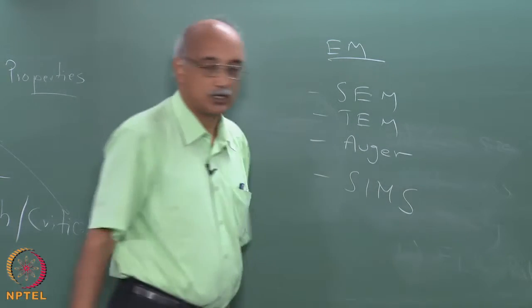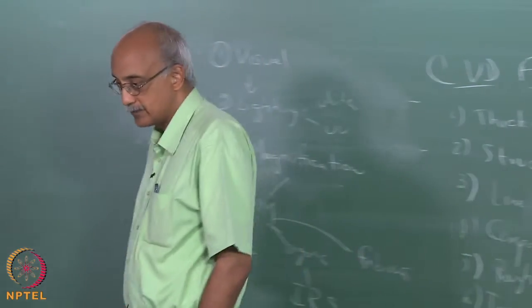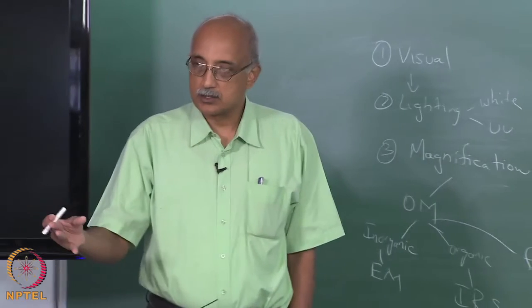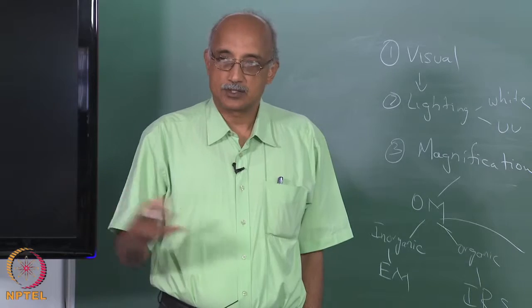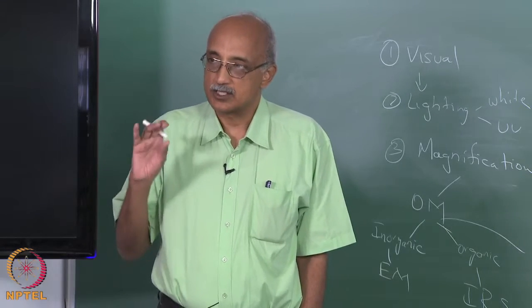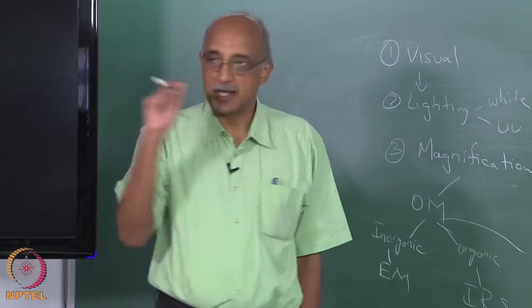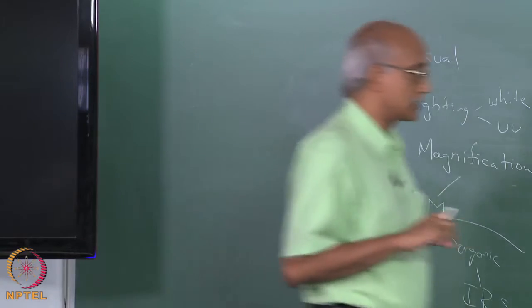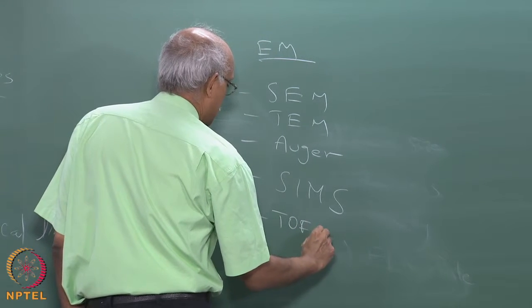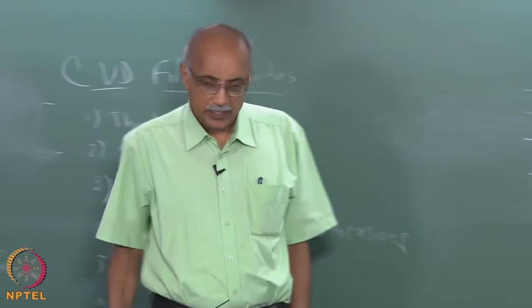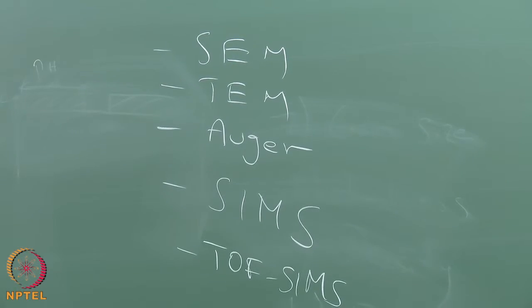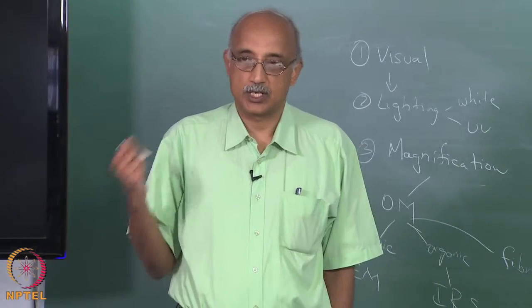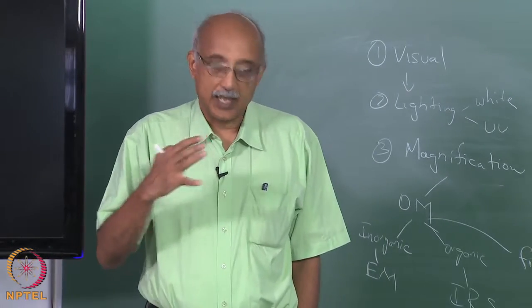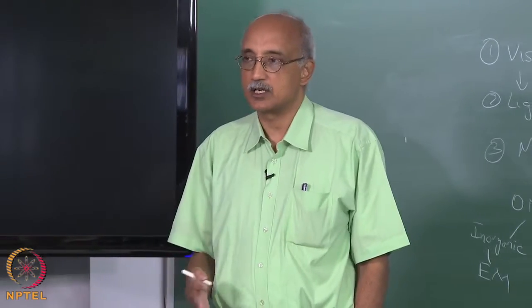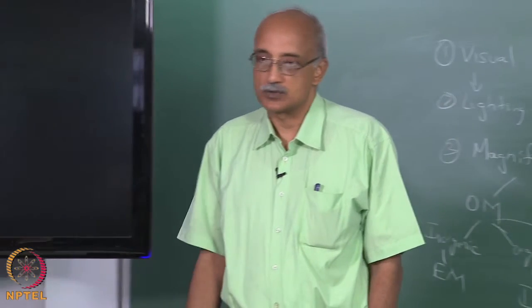The other method that is frequently used is SIMS, which stands for secondary ion mass spectroscopy. Here, essentially, you are using ions to knock off secondary ions from the surface, but the secondary ions are taken through a mass spectroscopy column where they are spectrally resolved to obtain the atomic masses of the individual elements. So this technique and another related technique called time of flight SIMS, TOF SIMS, they are kind of like Auger because they can give you this depth profiling, but SIMS and TOF SIMS have better resolution than Auger spectroscopy. So if you want, for example, angstrom level resolution of a CVD film in terms of its elemental composition, you use techniques like Auger, SIMS, and TOF SIMS to be able to do that.